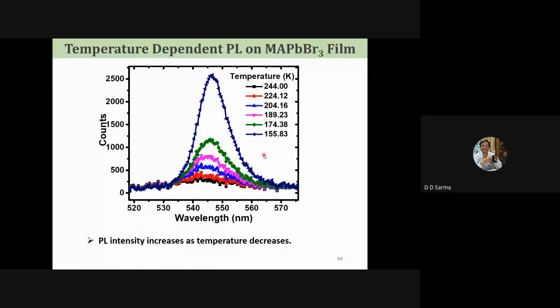And if you do the measurement, indeed, this is what I'm showing you, photoluminescence spectrum as a function of the wavelength for different temperatures. And you can see as my temperature goes from 155 Kelvin, to 174 Kelvin, 189, it keeps going down very rapidly. And so I can fit this and extract. But when I do that, there's a major problem. I do it on Monday, I get one result. I do it on Tuesday, I get a different result. I do it on Tuesday afternoon, I get yet another result. Every result is different. And that got us very puzzled for a long time.